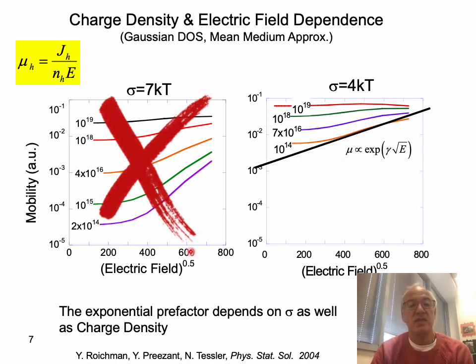traps. This crossing that jumped here before I was ready for it really is to remind us that what we see here is the classical example where you apply a model and you get a result. And actually, when we did that calculation, we were not aware yet that for sigma larger than 5kT, the mobility is not well defined anymore. And really, for 7kT, the mobility is not, if you like, a good quantum number, as one would say in different circumstances.